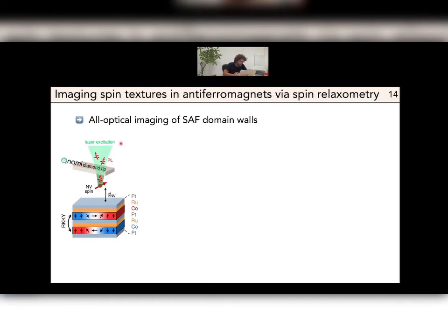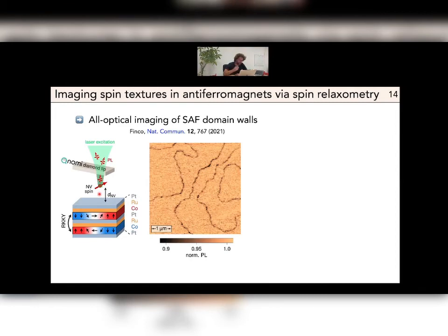So now this is the principle of the experiment. We rely on a diamond tip here, but we don't have any kind of microwave to apply. We just excite with a green laser and collect the photoluminescence. And this is a typical result that we can get on this sample. You see dark quenching lines here that are essentially localizing the position of the domain walls in the sample.